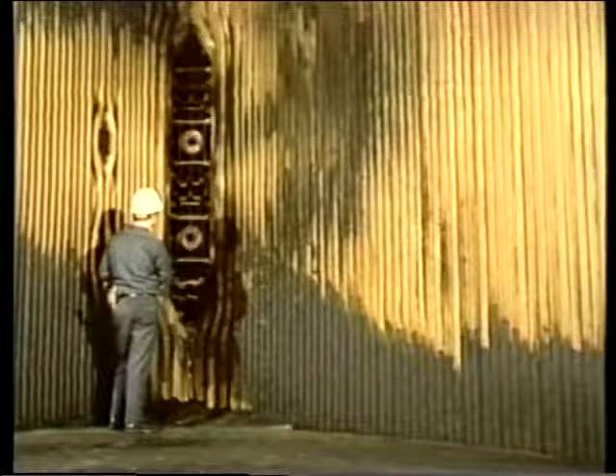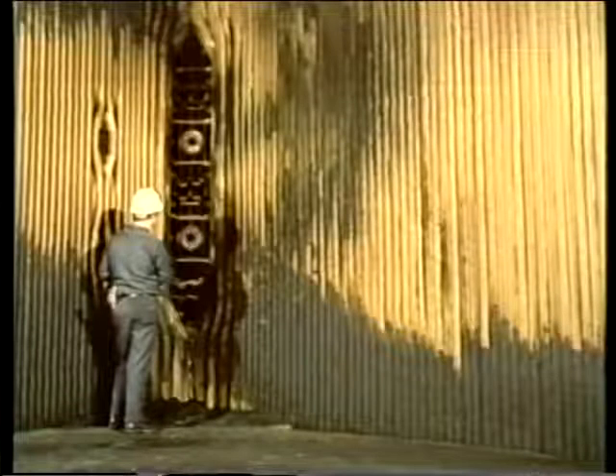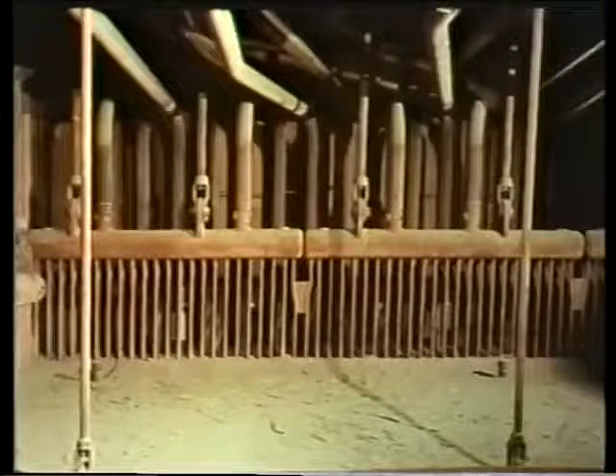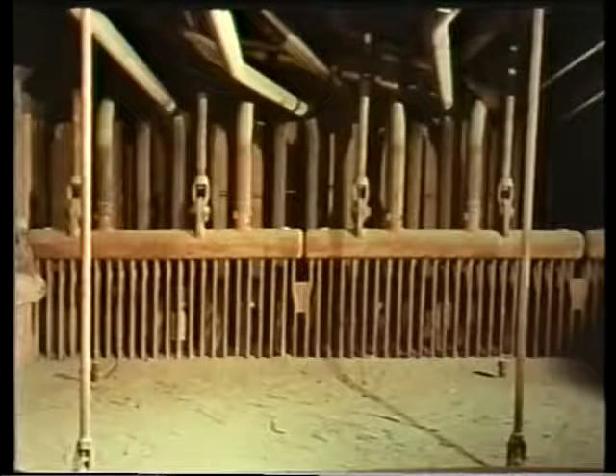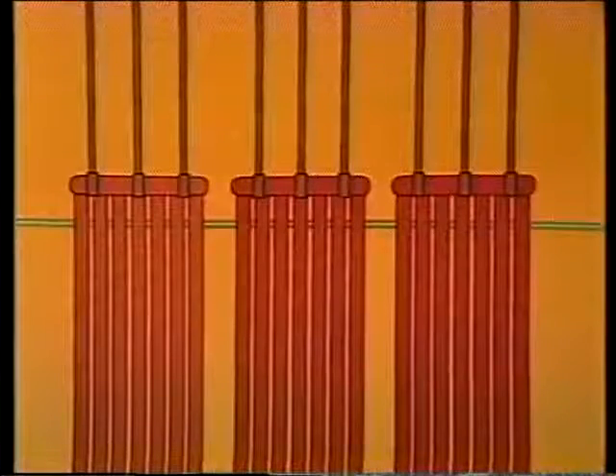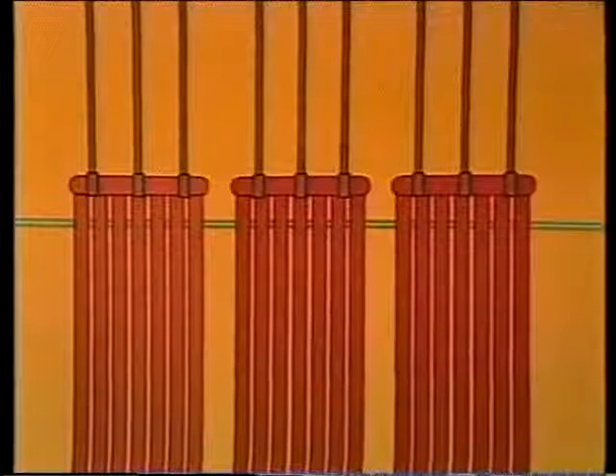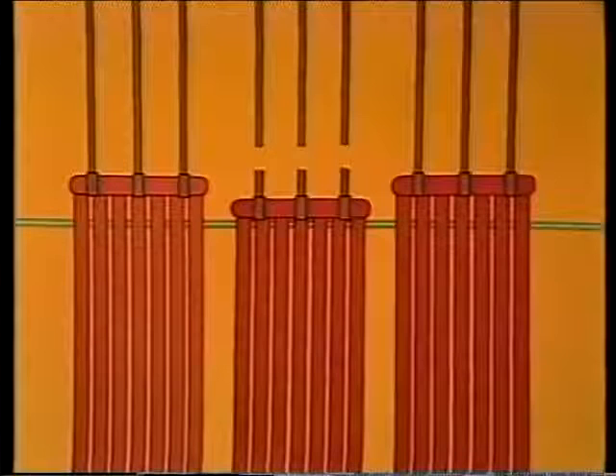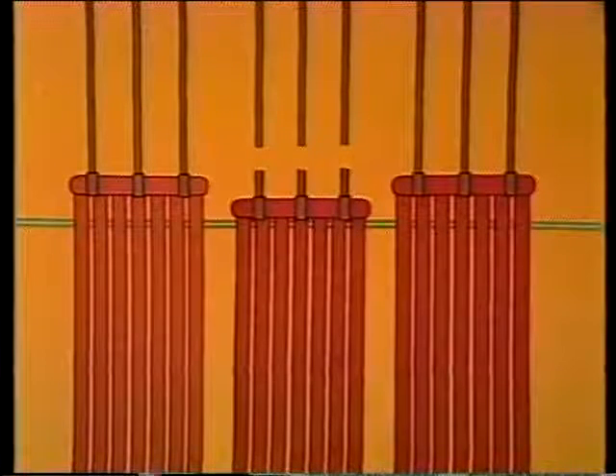Now, tube blisters, like these right here, are bulges in the tube surface, which form when the tube metal becomes so hot that it softens and is pushed out by the boiler pressure. Now, the next problem, support failure, shows up in the water walls as vertical misalignment of its tubes. Water walls are attached to headers that are usually hung from the top of the boiler. Now, if the supports holding up a section of the wall break, that section will sag. And if that happens, you'll see a section of tubes that is lower than the others. It's important to check this out because support failure could lead to the collapse of the entire boiler.